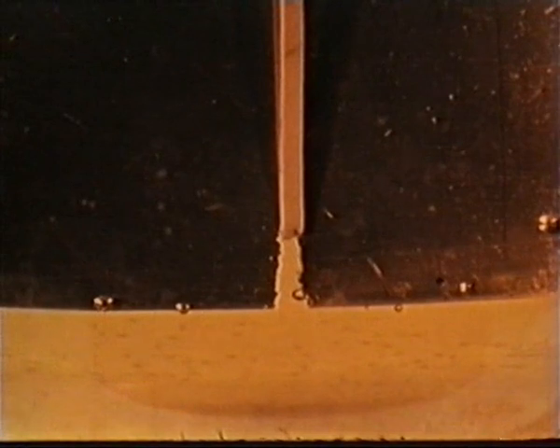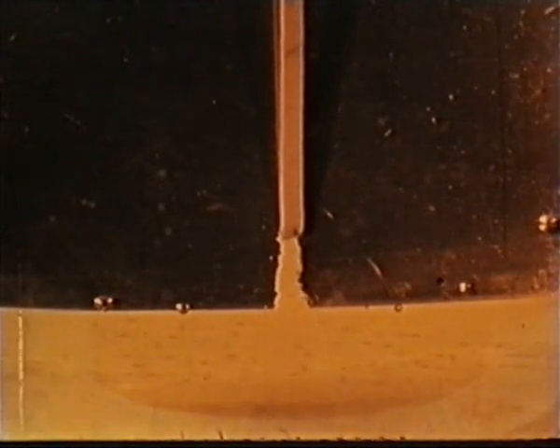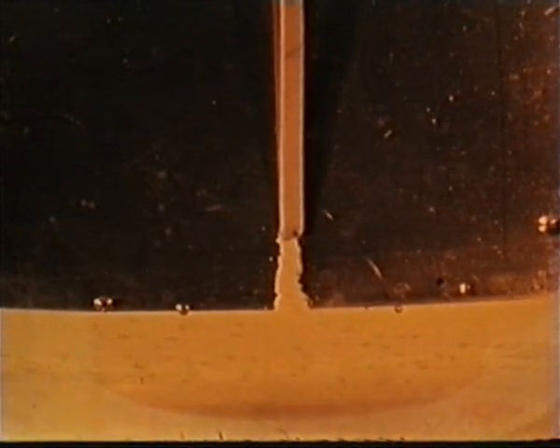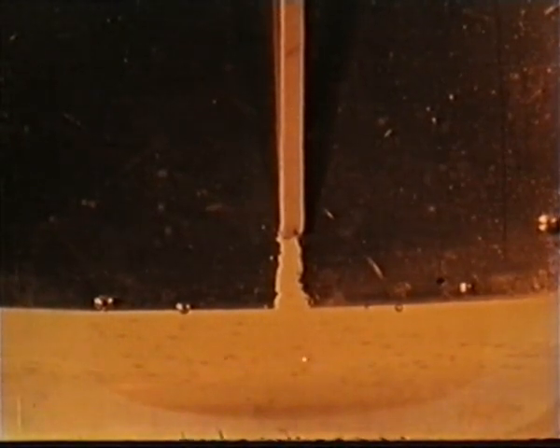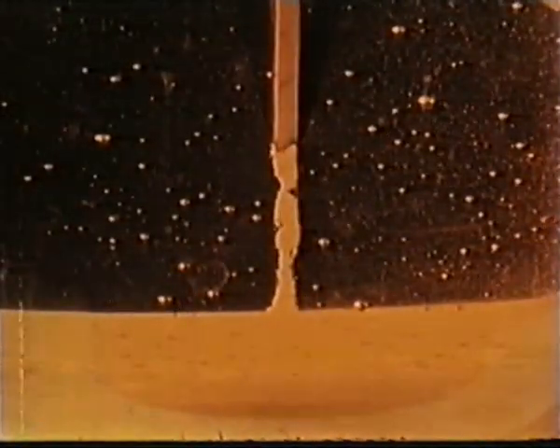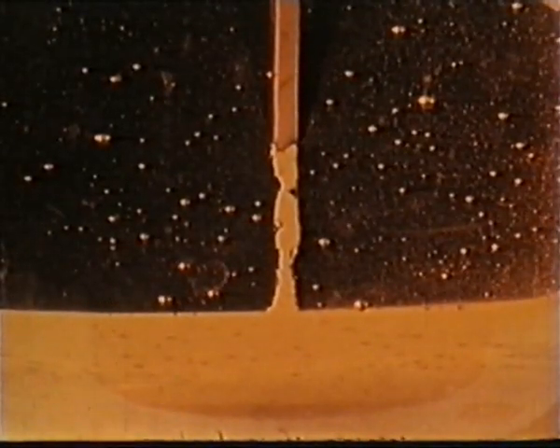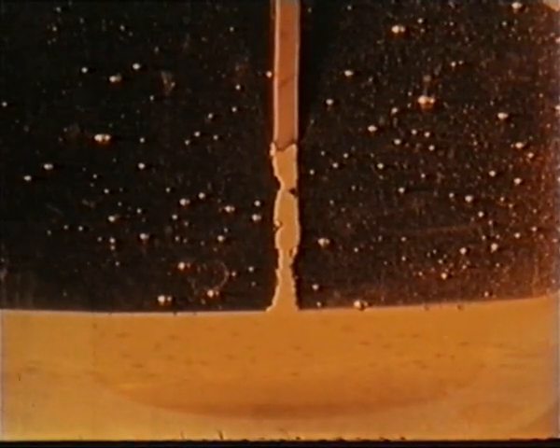By taking photographs after a period of time, we can see the rubber band cutting into the edge of the stainless steel. Oxygen cannot easily penetrate beneath the rubber band. Oxygen starvation causes the passivity to break down, creating an active area or anode beneath the rubber band, while the remainder of the surface being freely exposed to the dissolved oxygen acts as a cathode. Obviously, with passive alloys, it is necessary in some environments to avoid deposits or crevices which can exclude oxygen.